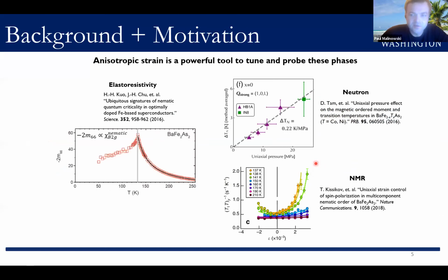So this raises the prospect that if we're able to tune these phases and their associated fluctuations and see how the superconducting state responds, we can gain insight into how all these phases are interconnected. And as it turns out, anisotropic strain is a uniquely powerful tool to couple to these phases. So for example, in the case of nematicity, measurement of anisotropies induced by anisotropic strain, such as elasto-resistivity, are a direct measure of the strength of nematic fluctuations above the ordering temperature. On an even simpler level, symmetry considerations imply that the nematic order parameter is directly proportional to the amount of external strain in the same symmetry channel. So by applying strain, we can enhance nematic order and thus suppress its fluctuations.